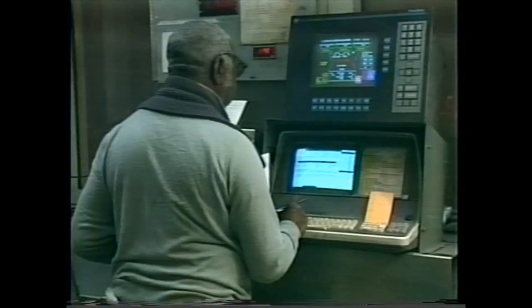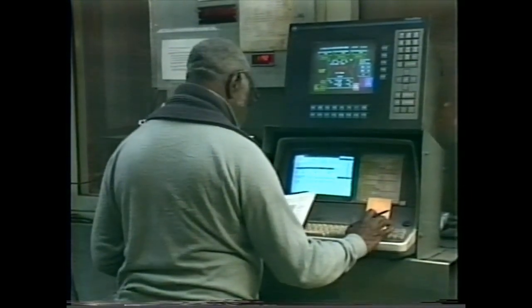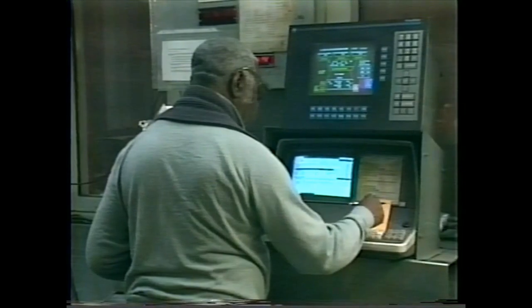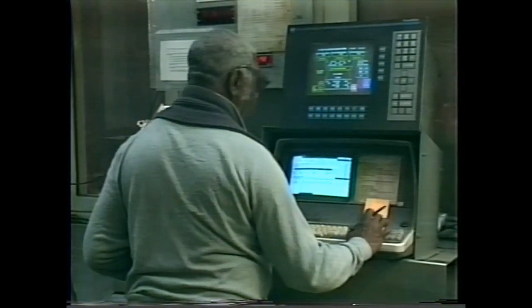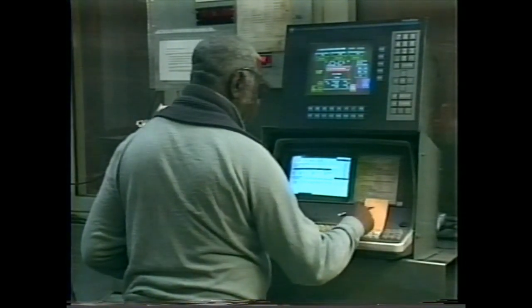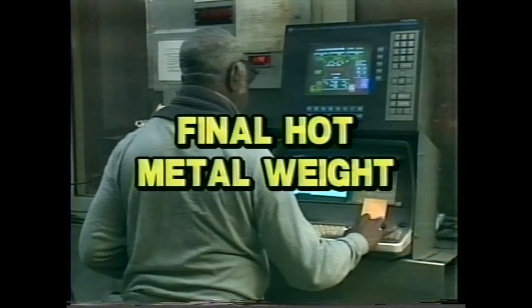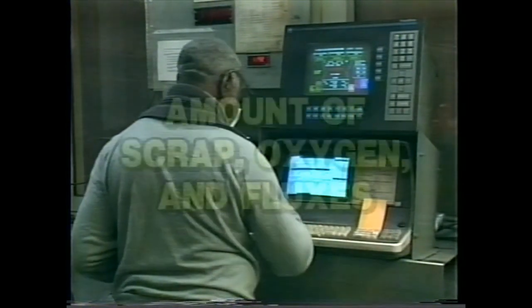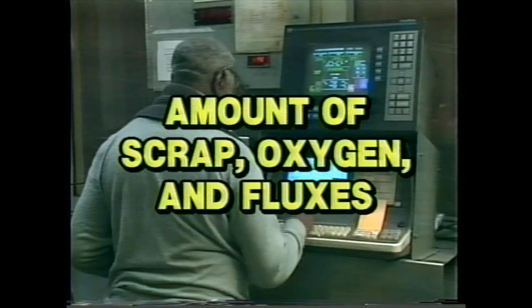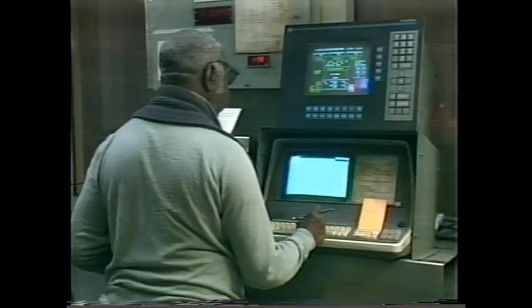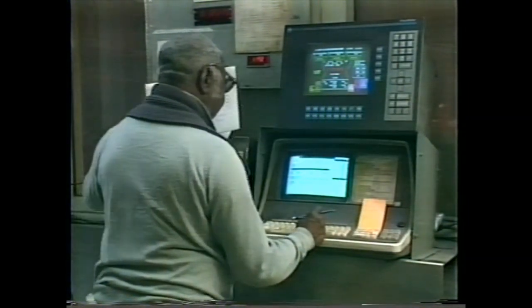The blast furnace analysis together with the hot metal temperature allows the pulpit operator to calculate the thermochemical balance. This balance is achieved by determining the final hot metal weight and the amount of scrap, oxygen, and fluxes needed to produce the grade of steel per the sequence number. The analysis of the white iron sample taken at the hot metal hole is used by the pulpit operator to adjust the amount of scrap, oxygen, and fluxes for the heat.